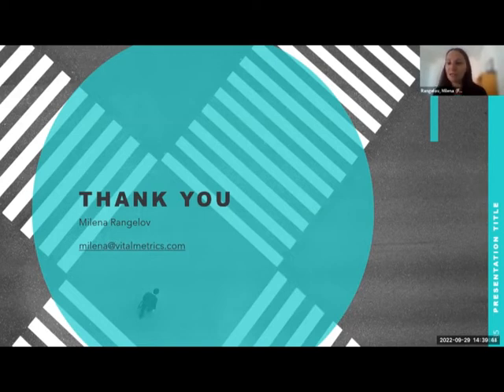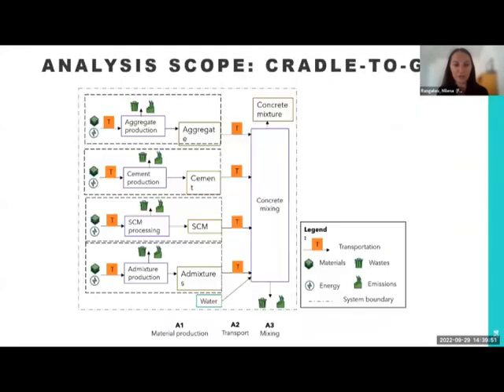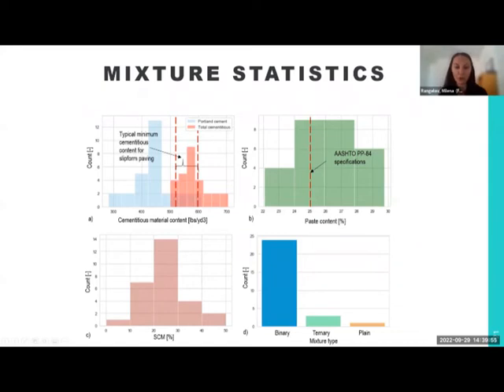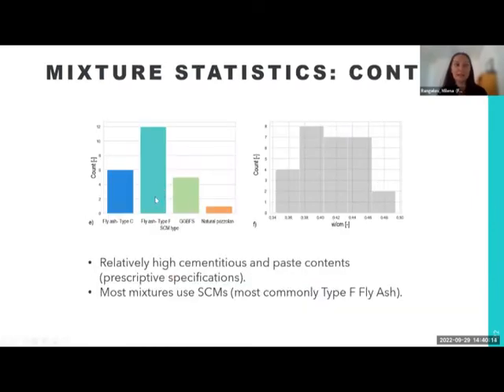The reason why paste is different than just cement is that, as you could see, and let me go back a few slides, I hope I don't make you very dizzy, we have all of these SCMs included, plus the water. So not every paste is equal. Let's say the Hawaii mix, because it's plain, only has cement and water. However, mixes in other states can have any one of these, most likely type F fly ash or type C fly ash or slag. Because of that, paste quality is not the same. Also, when we're speaking about environmental impact, cement is the most intensive, whereas these other things such as fly ash and slag are industrial byproducts, so they have much lower impacts than cement.